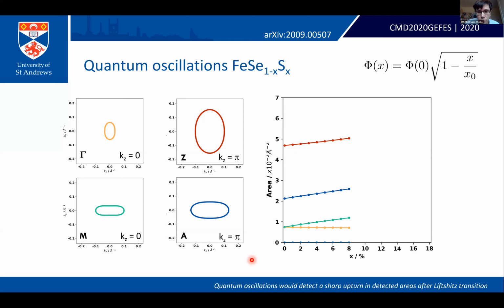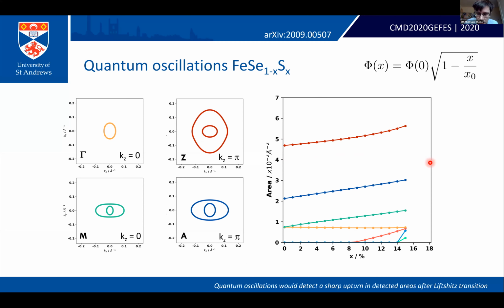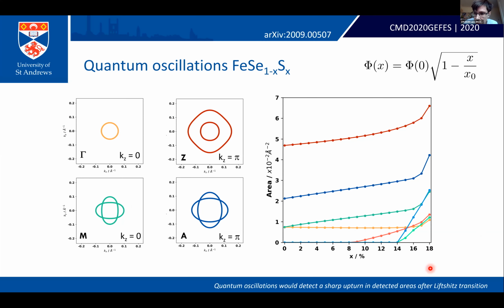What we find is that for a wide variety of the doping levels, very little occurs. These 4 areas that we can see here remain roughly constant with a slight increase. And a 5th area appears due to this inner hole pocket coming back above the Fermi level. But at this Lifshitz transition of the dxy electron pocket, which occurs in our model at about 14%, what you find is the presence of 2 new extremal areas from the Lifshitz transition, which sharply increase in size. And this sharp increase in size here would be a signature of this dxy Lifshitz transition.